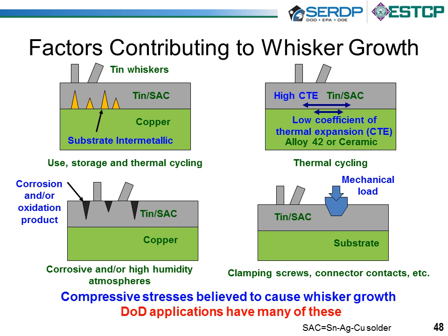And so when we look at whiskers and the study of mitigating whiskers, it makes sense to understand at least a bit about the observed factors that have contributed to whisker growth. Use and storage, where substrate intermetallic grows between the substrate and the tin, is a key factor. The nice thing about that one is that it's on the radar screen for the industrial controls people and the long-term server people. That's good for the DoD because we can pay attention to the studies going on in that realm and benefit from that. The other place is clamping screws and connector contacts. That is also important in consumer electronics: press-in connector pins, edge-mounted brush connectors, and there's a fair amount published on that. So the nice thing about that is the DoD didn't have to go figure that out.